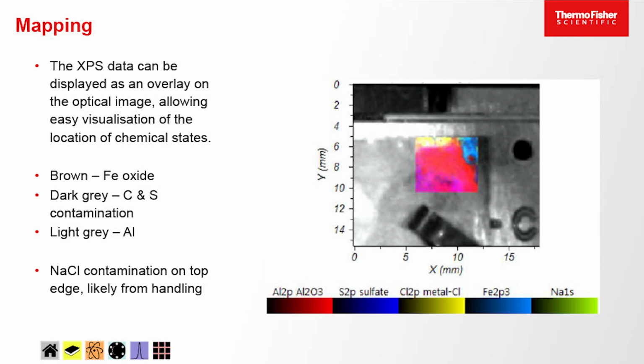And we can also, just to confirm things, overlay the XPS data onto the optical image. So we get these nice color plots showing the locations of the different components. So chloride there, aluminium oxide here. We can see that sulfate is overlapping with the aluminium here, and then the iron over here in the staining. So again, by using the imaging, we can look at the distribution of these chemistries across the surface, identify things that we couldn't see optically, and also confirm what we suspected about the dark staining on the material.